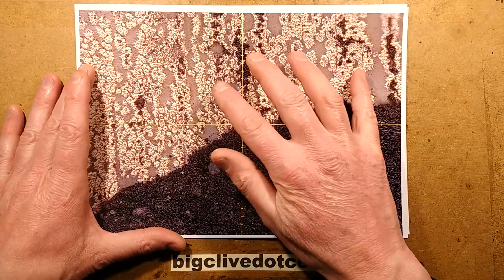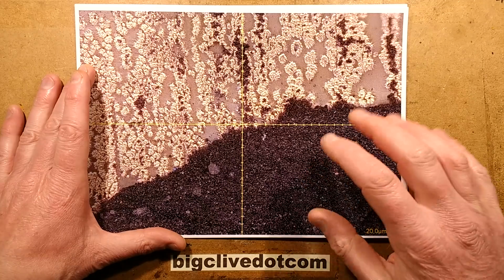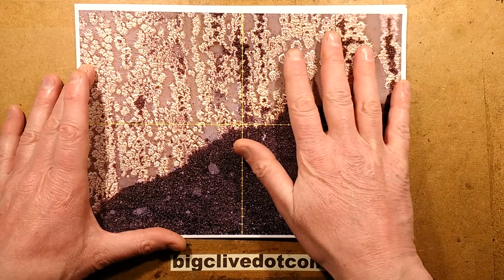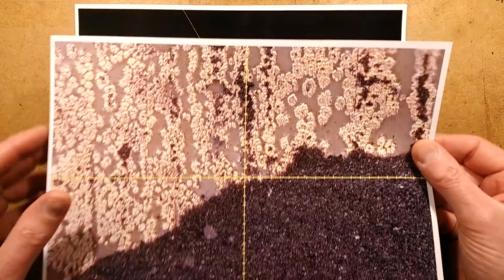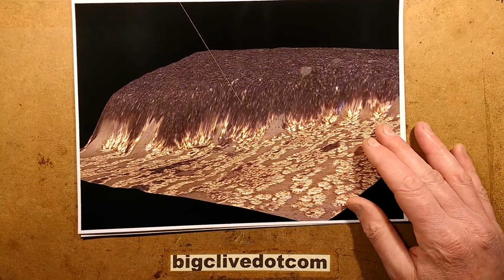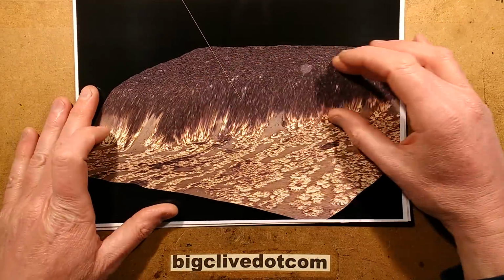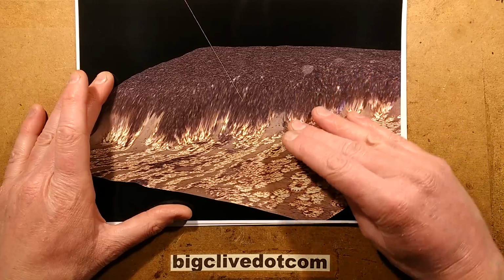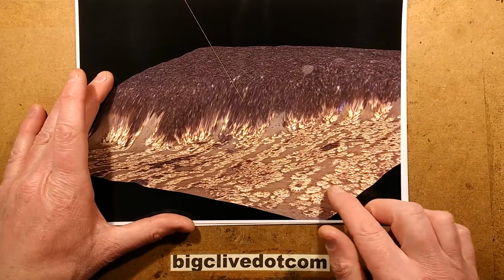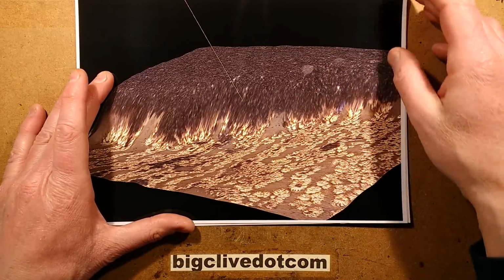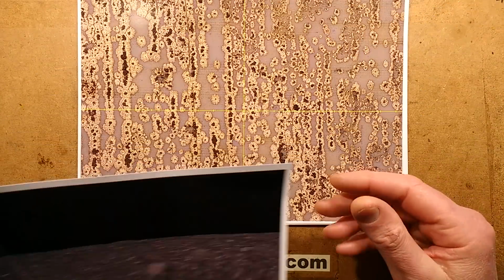Those are the little islands of copper that have transferred from the electrode through that and onto the actual plastic separator. There's another picture which shows a three-dimensional effect. So that's the thick layer of the graphite material, and then it's coming down onto the plastic separator itself, showing all those wee islands. Lots and lots of little islands.